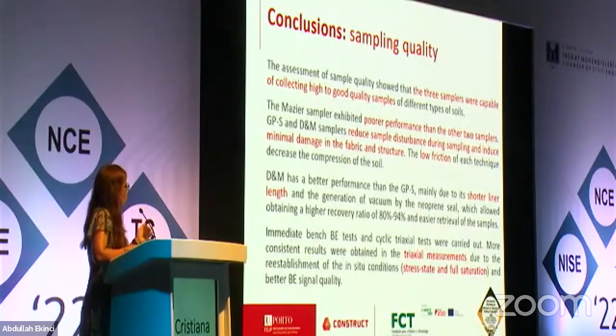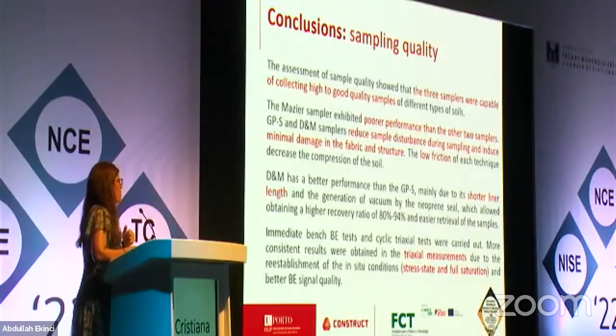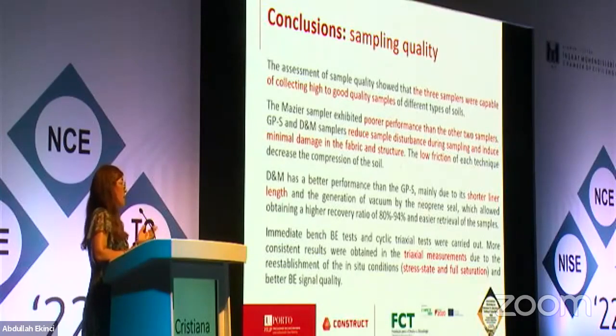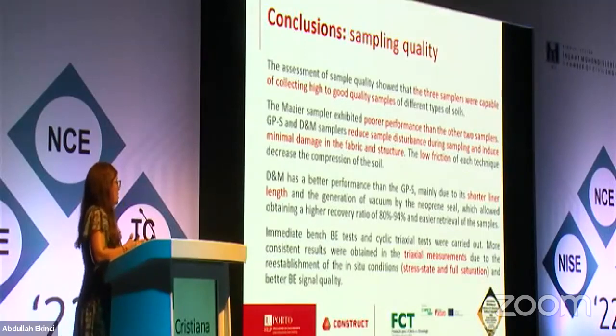The Dames and Moore had a slightly better performance than the gel push sampler because it has a shorter liner, it's only 15 centimeters, and the other one is 1 meter long. And also by the generation of the vacuum with the neoprene seal, and that justifies a higher recovery ratio for this sampler. The immediate bench tests compared against the cyclic tests show some discrepancies, and these are attributed to the need to reestablish the in situ conditions.